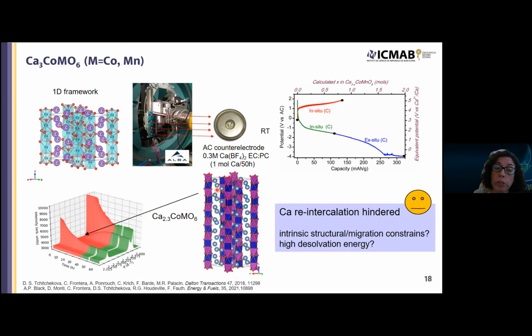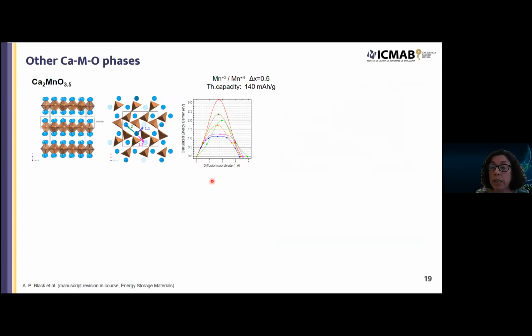Maybe the migration of those calcium ions in this oxidized crystal structure is more hindered than in the pristine one, or it may be due to the fact that to reintercalate calcium, you need to desolvate the ions from the electrolyte, and maybe the desolvation energy has a role to play here. So this is something that we're still trying to address.